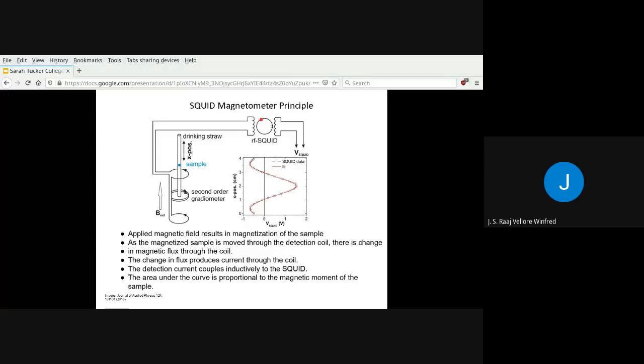And the detection current, as it is coupled into the SQUID, and then any change in the voltage fluctuations that is measured would result in a graph that is typically shown over here. As you move the straw, or as you move the sample position, your voltage measured across would show such a typical curve. The area under this curve is calculated, and that area is proportional to the magnetic moment of the sample.